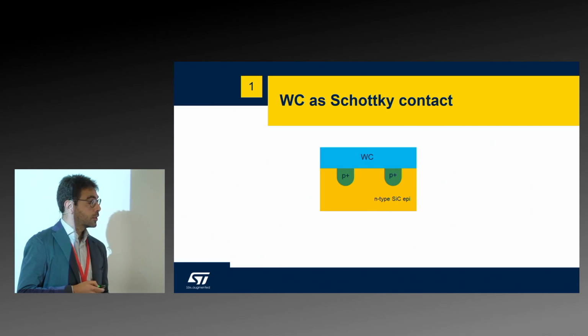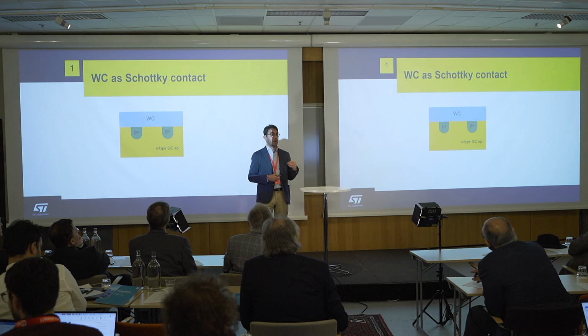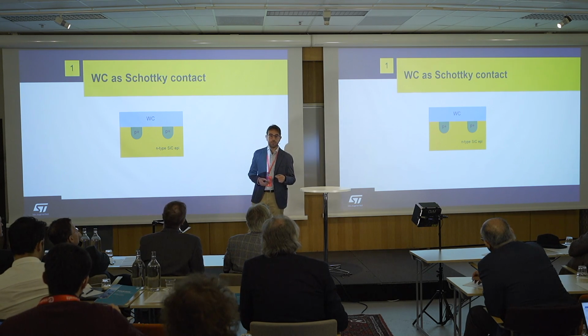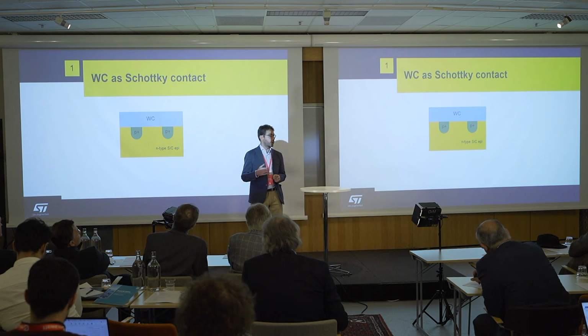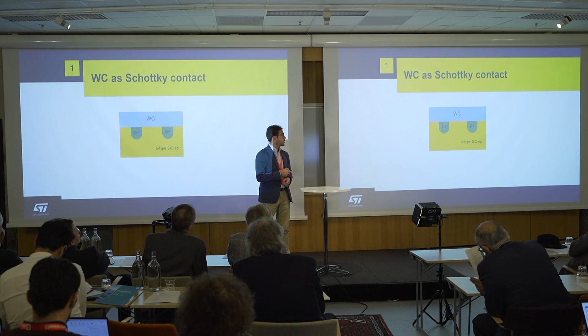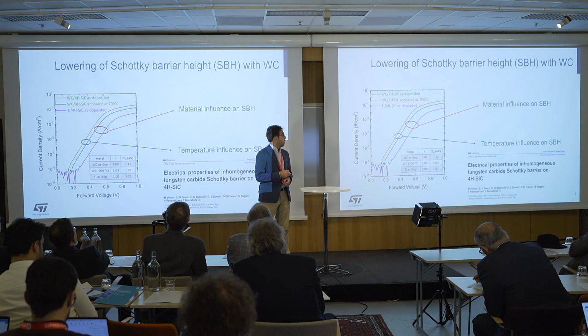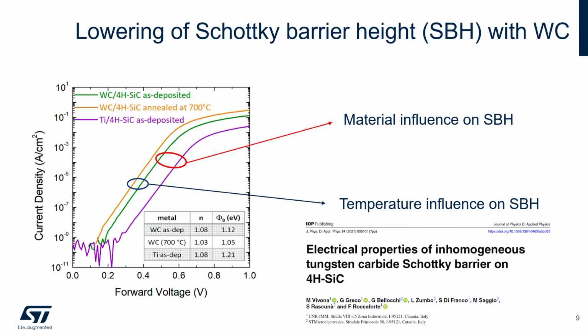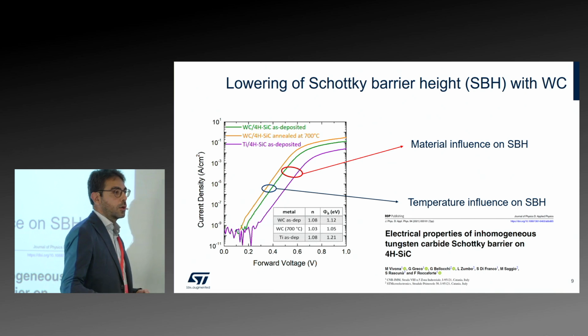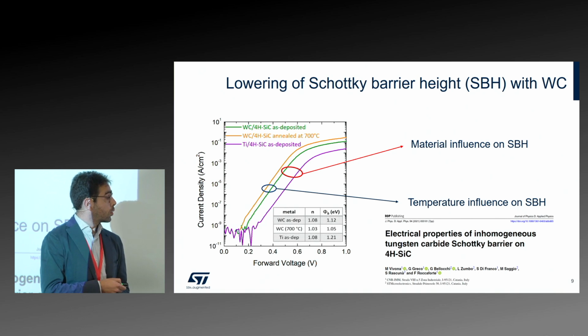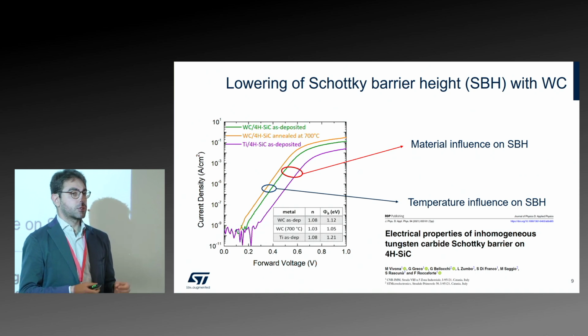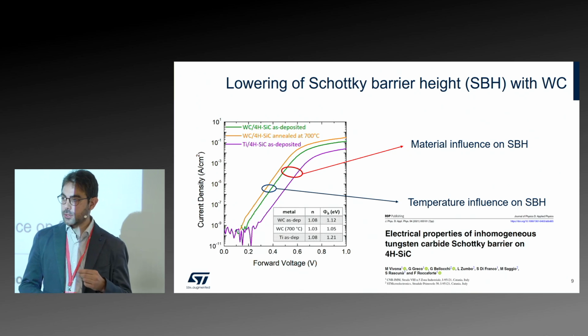So the first is, let's consider changing the materials. Our JBS diodes are made with titanium, 80 nanometers thick, as the Schottky barrier. We explored other metals, one of which is WC, tungsten carbide. Just putting tungsten carbide on top of our silicon carbide wafer with the same process, we obtain a lower Schottky barrier height, from 1.2, which is the typical value for titanium, to 1.1. And a lower Schottky barrier height means lower VF at the end of the day. And if we look at the ideality factor, it doesn't change, which means that the quality of my Schottky contact is really good.